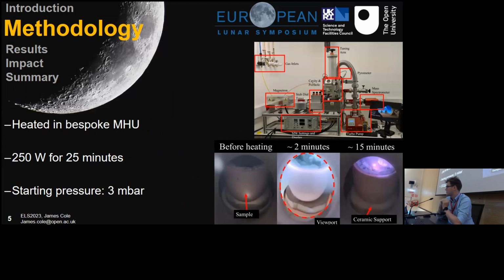So as Mahesh has already said earlier, we do have a bespoke microwave system at the Open University, which allows us to heat up samples in a vacuum environment. So I used 250 watt microwaves. I was going for the lower end of what's possible with our system. The main reason for this is I wanted to use what could be possible with a modern day rover or lander platform. And then I heated them up for about 25 minutes initially, and about 90% of the water was extracted.